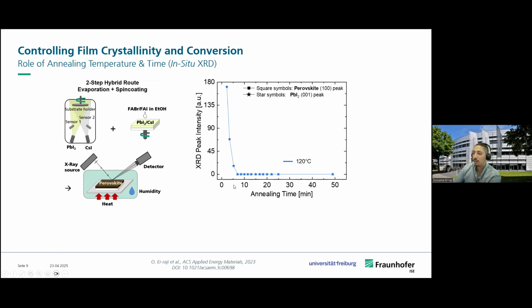But as the annealing time goes by, the reaction happens, and in around 7 minutes we have a full conversion from the lead iodide phase to the perovskite phase. Here you can see that the perovskite peak then starts to increase.